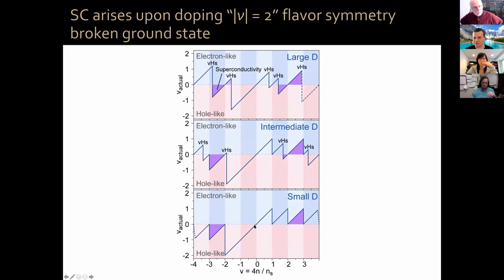So at small displacement fields, you have these resets, and superconductivity occurs between 2 and 3 or between -2 and -3. At large displacement field, a Van Hove singularity kicks you in the reset to the hole doping region, and superconductivity occurs when you dope with electrons or with holes this spontaneously flavor polarized state with 2 Fermi surfaces.